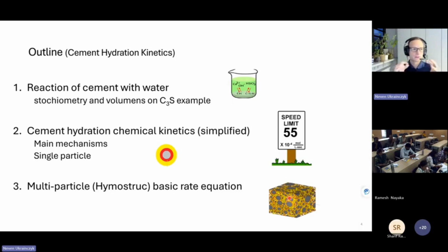I mean, the individual degree of reaction you have. So you will see that you have actually now to calculate all these properties, the degree of reaction per each fraction. So per each size fraction, you have to calculate the degree of reaction and then sum it up, and then you get the total overall degree of reaction.